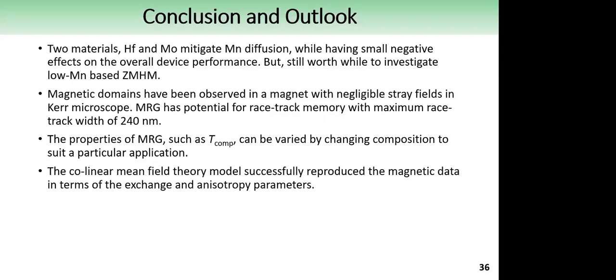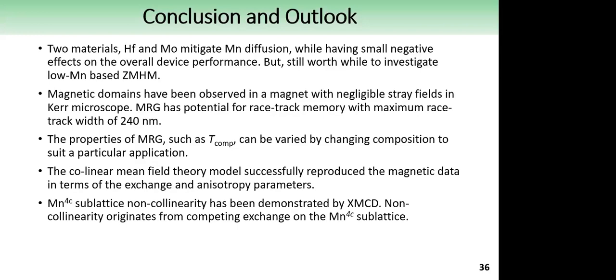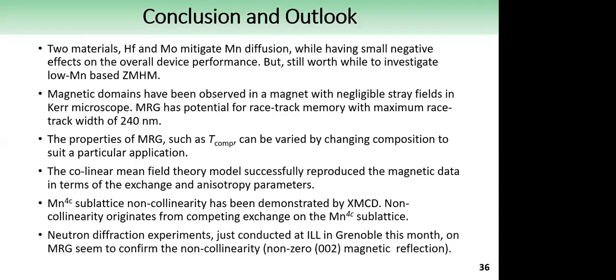The collinear mean field theory model successfully reproduced the magnetic data in terms of the exchange and anisotropy parameters. However, 4C sublattice non-collinearity has also been demonstrated by XMCD, and this non-collinearity can originate from competing exchange on the 4C sublattice. Neutron diffraction experiments just conducted at ILL in Grenoble this month, also on MRG, seem to confirm this non-collinearity. We have observed signal on the 002 purely magnetic reflection, which indicates there is a component of the moment in plane with no applied field.